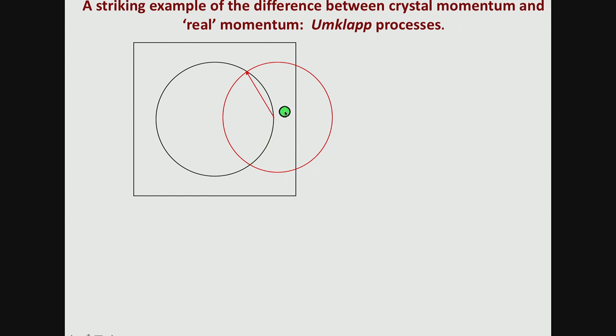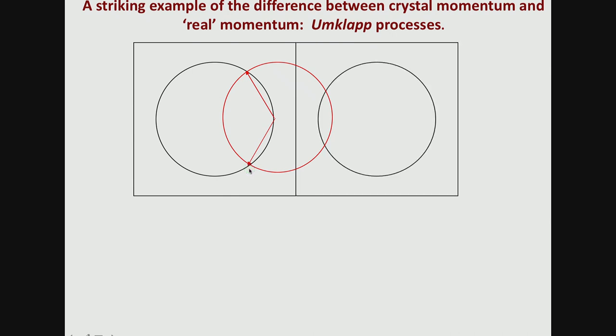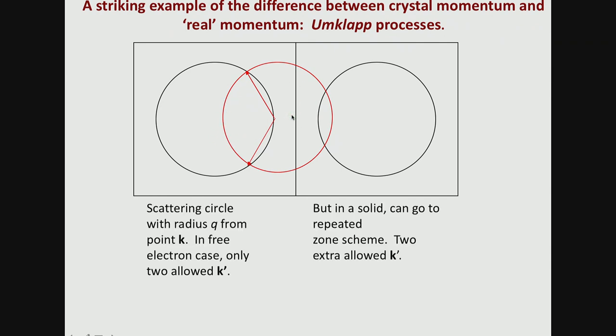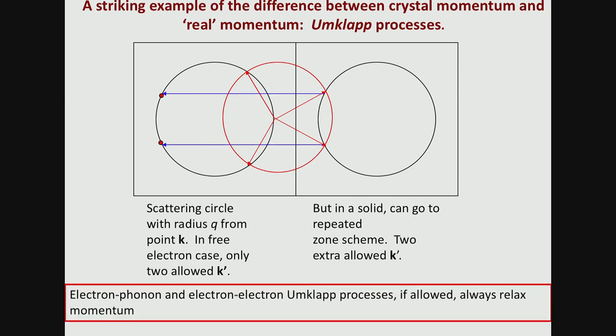So you imagine you have an electron sitting on the Fermi surface, and you have some scatterer, whether it's another electron or a phonon, which is able to scatter through mod k or mod q, which is that radius. That gives you a circle of allowed scattering events. And if you were just in free space, if you were of this radius, because you need to conserve energy, you could only scatter onto two points on the Fermi surface. Right? However, that's not true, because in a solid, you have crystal momentum. So you have to think about the Fermi surface in the repeated zone scheme. And that same radius of circle can be scattering you from the first zone to the second zone.